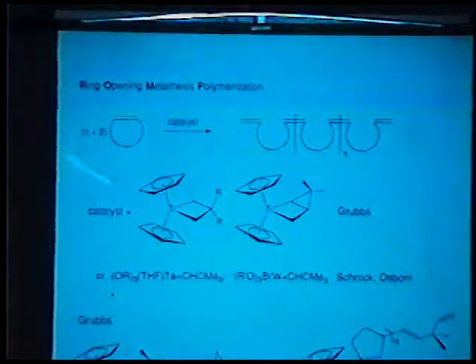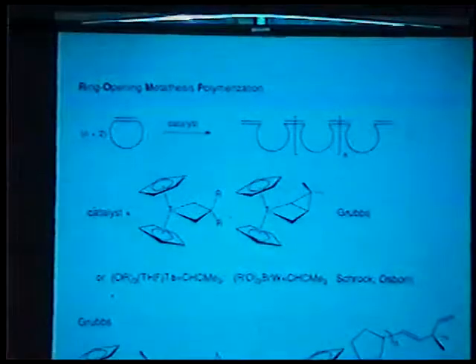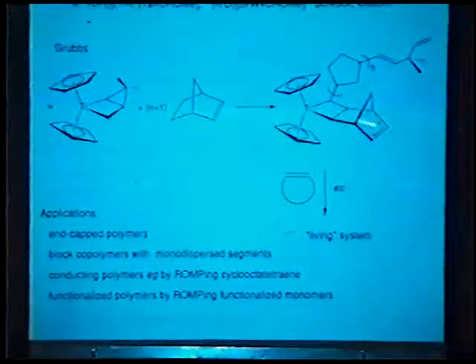Grubbs has explored, at least initially, some of these titanocene metallocyclobutanes as precursors to the catalytic system, entering from the metallocyclobutane part of the metathesis scheme. And probably if one introduces strain in the metallocyclobutane, for example, using this precursor, you can effect polymerization to give monodispersed polymers of the type shown there. There are a couple of mistakes. This double bond should not be a double bond. The single bond bracket should really extend out there.